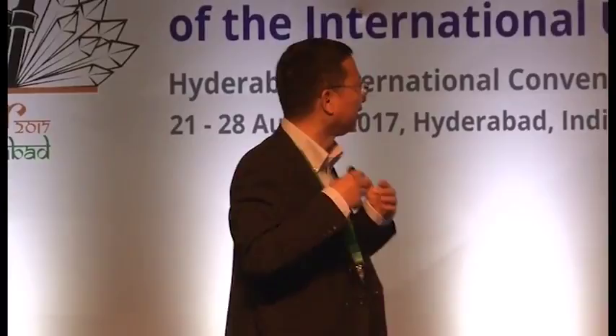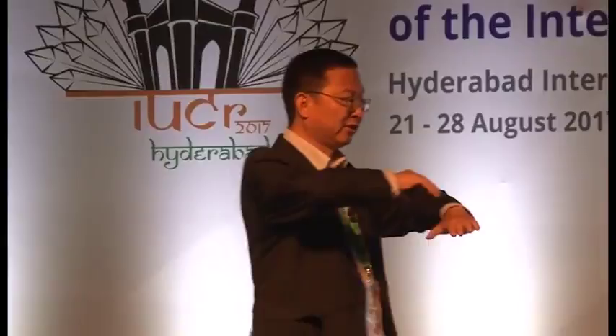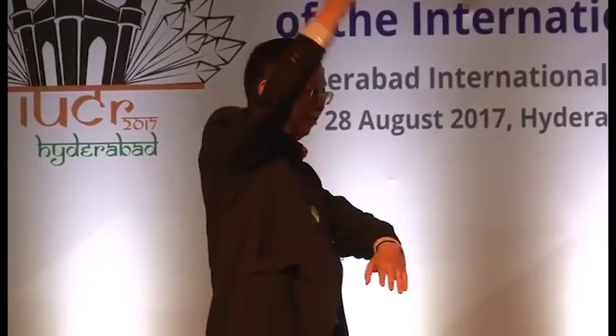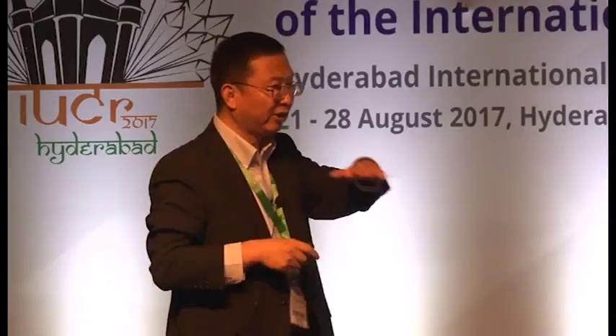For the dysprosium compounds, if we wish to get better uniaxial anisotropy along the axis directions, the axis and the equatorial ligands have some effect. And actually, I just mentioned the charge density from axis direction is much better. If there are no equatorial ligands, we should get the best performance.